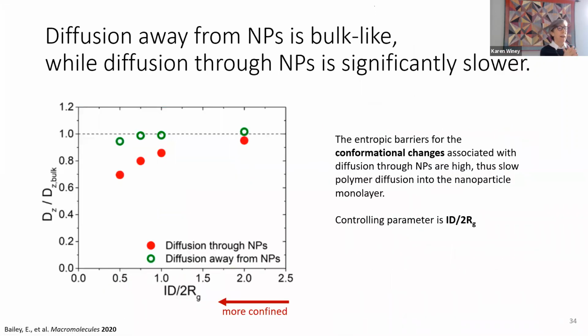And so that's these data. So we have the diffusion coefficient. It's just about what you'd expect for the bulk if you're going away from the nanoparticles. And if you're going towards the nanoparticles, things are slower. And again, it gets more significant as you go to more confined systems. And we're using here this parameter, ID over 2RG.